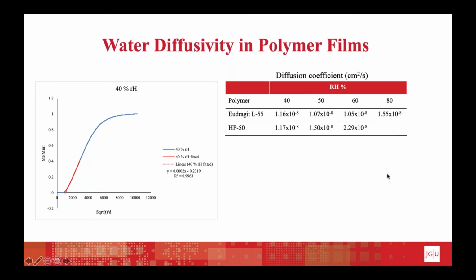And with a higher diffusion coefficient, of course, the permeability through this film would increase. So with low values, we are good to protect our dosage form. This can also play an important role, for example, in solid dispersions or solid amorphous dispersions, because water can act as a plasticizer in polymer films. If we had a high diffusion coefficient, it would mean that more water could be taken up into the polymer and change the glass transition temperature, and accordingly affect the stability of the solid dispersion. But that's for the assessment of the water diffusivity as the first example.